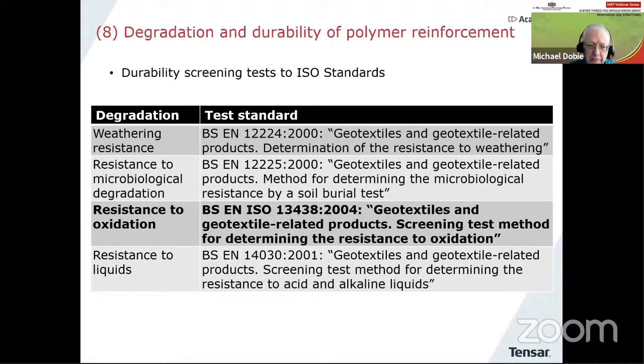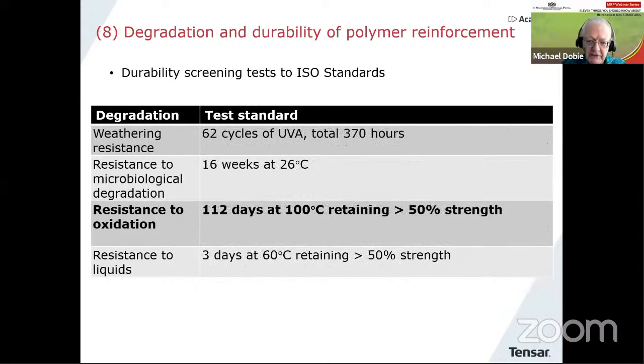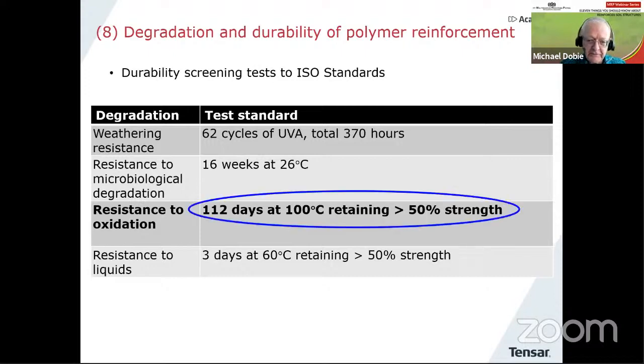You can see there those four main degradation procedures: weathering, microbiological, oxidation, and resistance to liquids, acids and alkalis. And those are their titles. We don't need to read those today, but just a brief mention here. These are the targets you're trying to reach in each of those. I'd have to say, on the whole, they are not particularly onerous. If we look at oxidation there, after 112 days at 100 degrees centigrade, you need to retain 50% strength. Well, 50% is half. That's not a very wonderful target for a typical polymer reinforcement, even under those conditions.